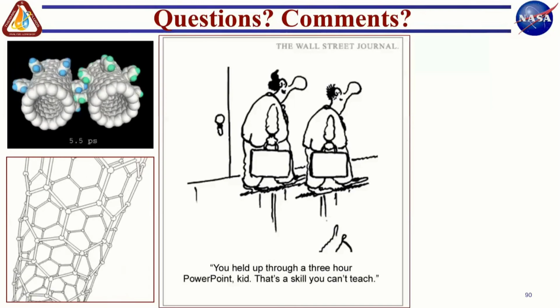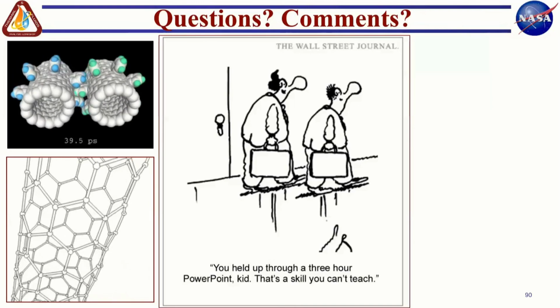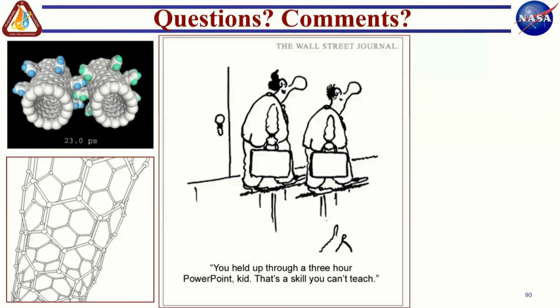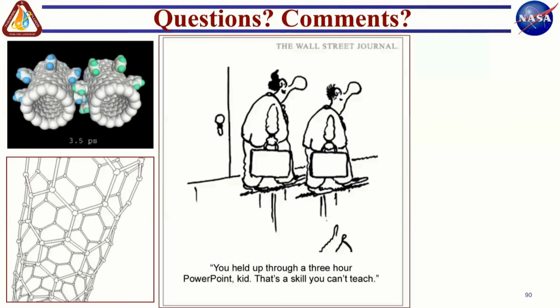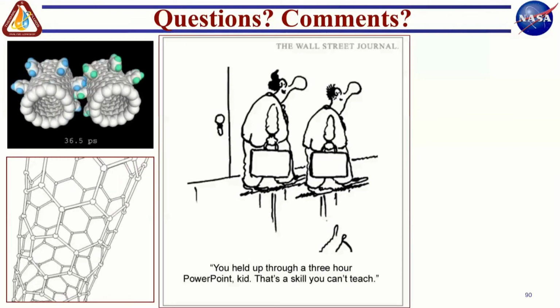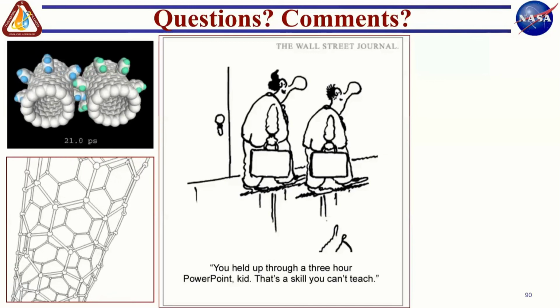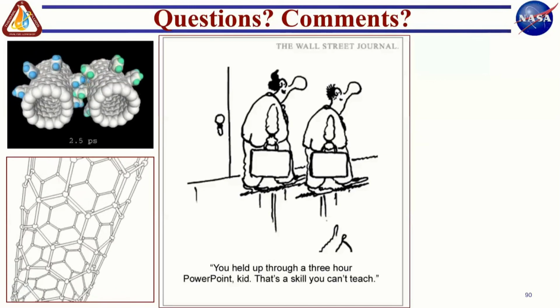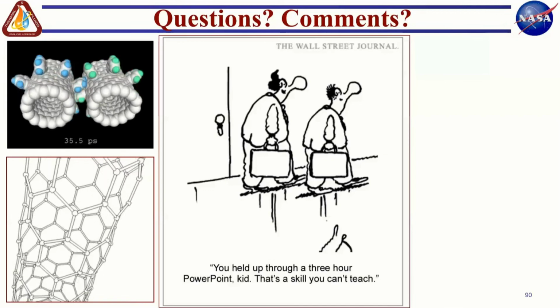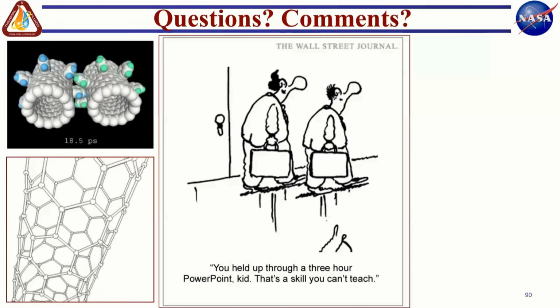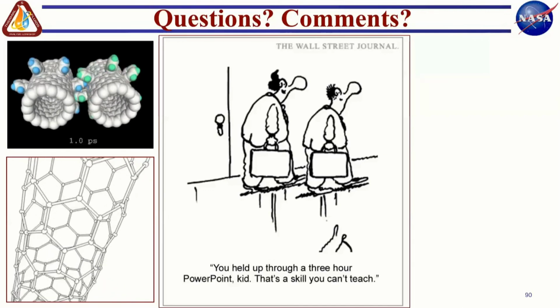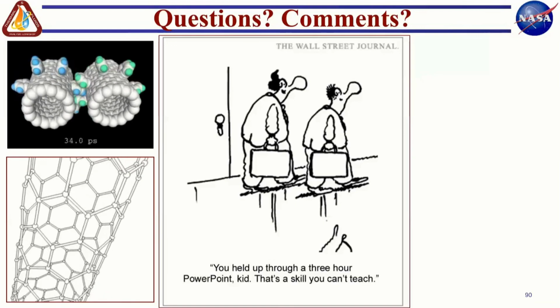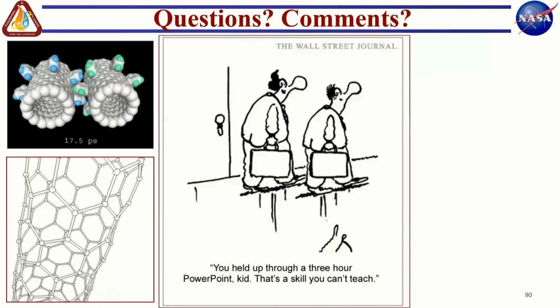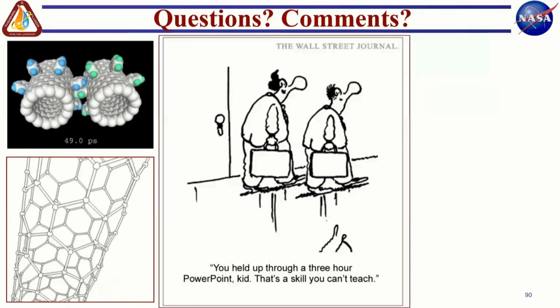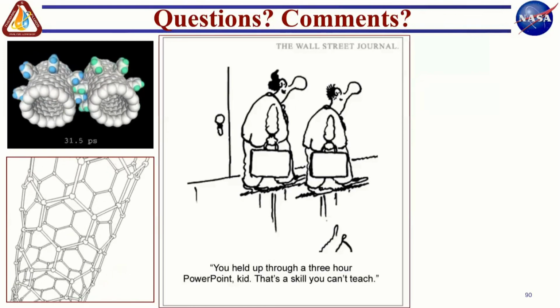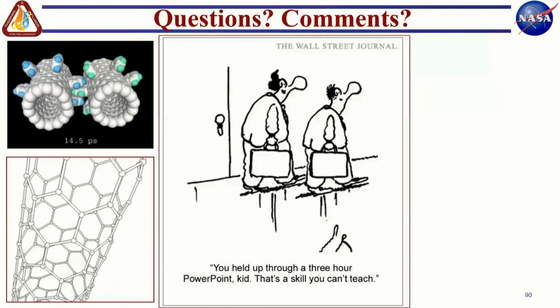You can think of it this way. If you have trapped a lot of hydrogen ions on the surface of the nanoparticle, this nanoparticle is now net positive compared to the bulk fluid. So when two nanoparticles are approaching each other, in addition to the van der Waals interaction, they are also sensing that there is a repulsion from a positively charged particle as they come closer together. And so that guarantees their stability, because that prevents them from touching each other and agglomerating.